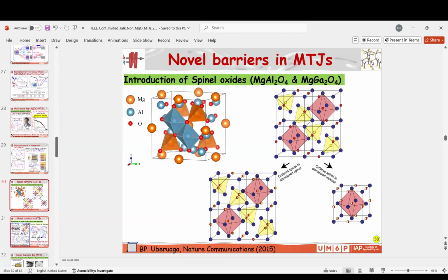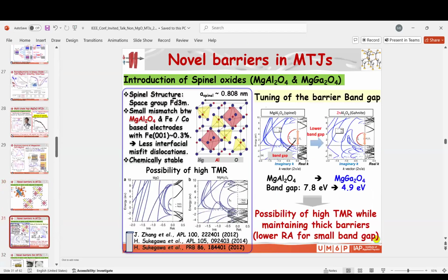According to the theoretical calculation, it is similar to MgO, so there is nothing new. The spin filtering exists. The decay of delta 1 is smaller than delta 5 and delta 2. And the good point here is that the lattice match with iron, for example, is 0.3. I want to draw your attention to the fact that if we modulate, for example, the composition of magnesium aluminum, a little bit magnesium rich or a little bit aluminum rich, we can get a lattice match with other ferromagnets, which is not the case for MgO. Also, we have many candidates.